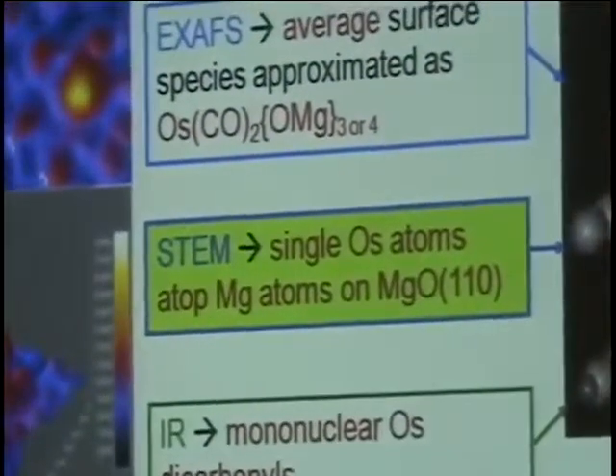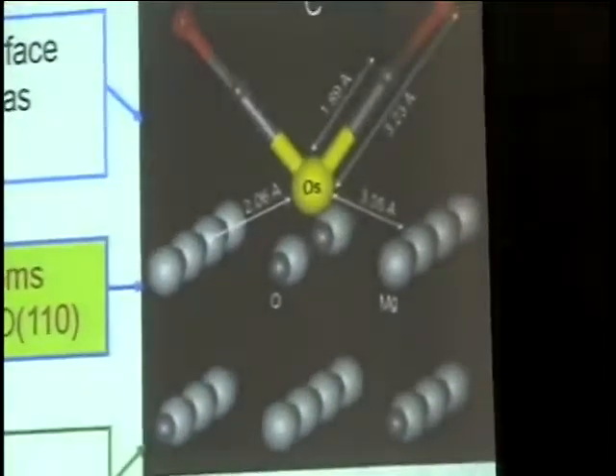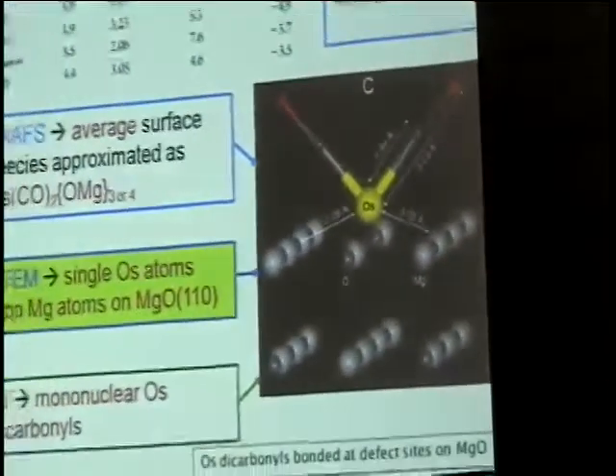So what's important in this is that if we look at the osmium on one particular face, it's the 110 face of MgO. That's especially, we're going to keep coming back to that face, especially good for structure determination. And what we find is that the osmium atoms, I don't think you can see it well enough from this image, but the osmium atoms are atop magnesium atoms, or columns of magnesium atoms. So if you take a top view, you're looking down on columns of Mgs and columns of Os. And so it maximizes the contrast, and it turns out that the osmium atoms are directly above columns of magnesium atoms. So that gives us a basis for determining a structural model.